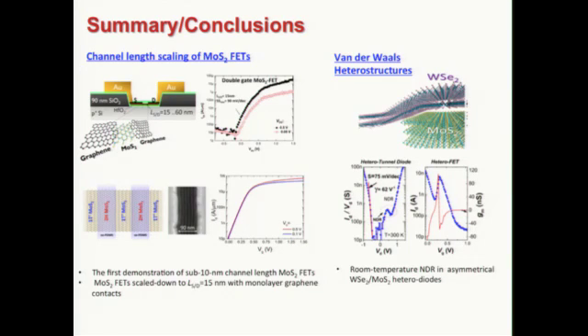Sorry. The other question is about the mobility. I remember you showed one slide about mobility. Do you understand what gives you the mobility? Generally, in semiconductor, in silicon, the mobility has two main mechanisms. One is phonon, the other is disorder scattering. But in 2D material, do you have some understanding? We actually have the same thing here, plus interface effects, because they're very thin. They can be easily affected by trap charge at the interface, by defects at the interface with the oxide. Also, if you are using high-k dielectric material, where you have soft phonons, it can also lower the mobility.